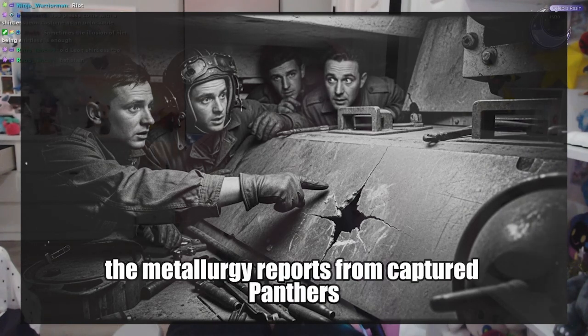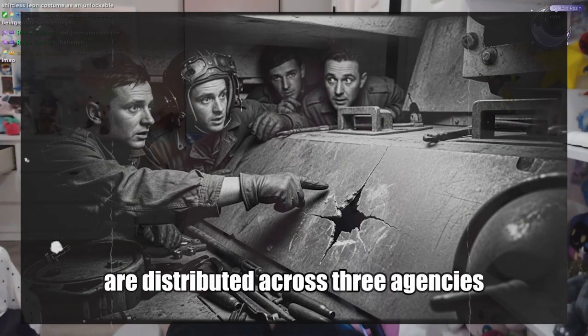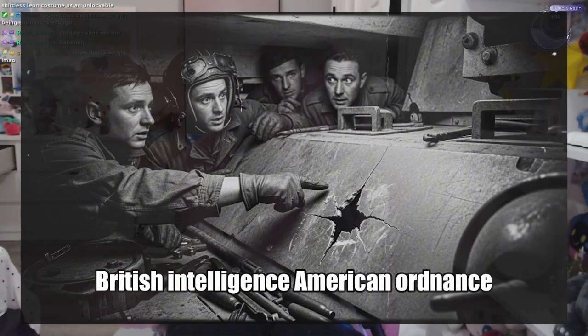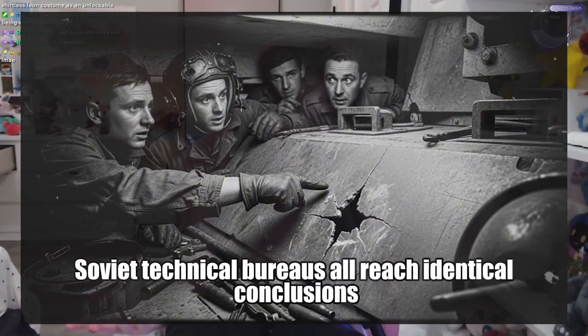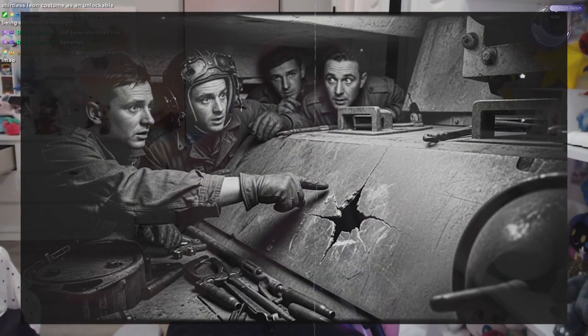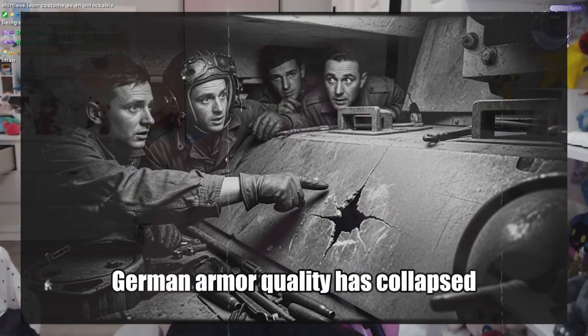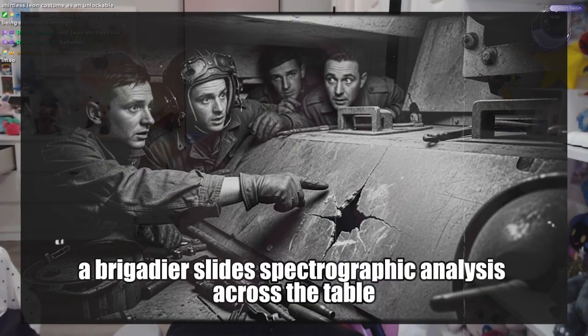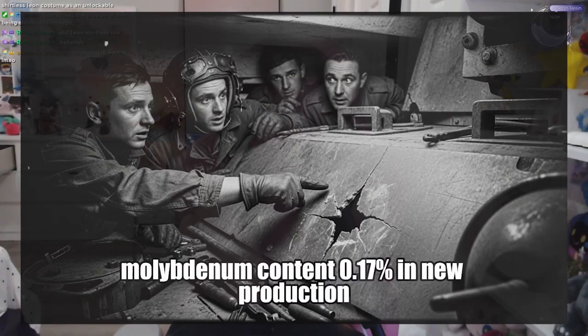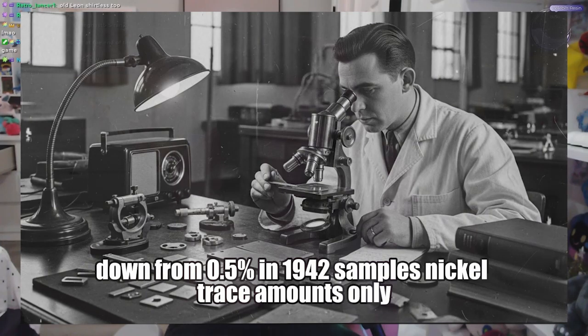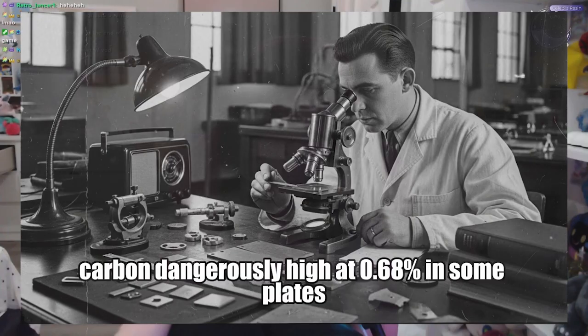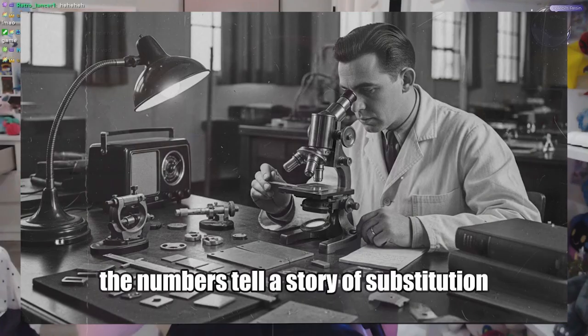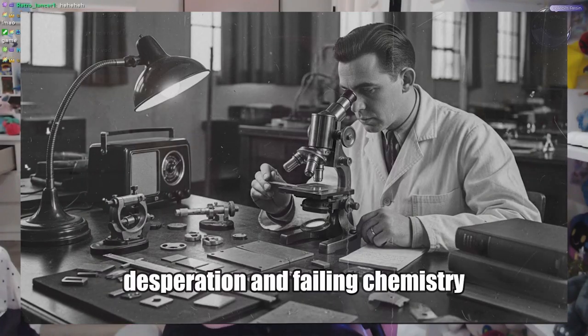The metallurgy reports from captured Panthers are distributed across 3 agencies: British Intelligence, American Ordnance, Soviet Technical Bureaus. All reach identical conclusions. German armor quality has collapsed. A brigadier slides spectroscopic analysis across the table. Molybdenum content 0.17% in new production, down from 0.5% in 1942 samples. Nickel, trace amounts only. Carbon, dangerously high at 0.68% in some plates. The numbers tell a story of substitution, desperation, and failing chemistry.